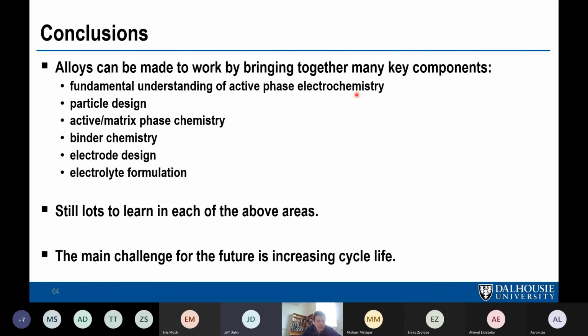So let's see what I said 3 years ago. You can get these things to work half decently, but you have to bring together the fundamental understanding of silicon electrochemistry. That had to come first, and then particle design to make the particles work. What's the interaction between the active phase and the matrix phase, whether it's a silicon alloy or SiO, you have the stress voltage coupling and other effects that can change the voltage curve, binder chemistry, design of the electrode, the electrolyte formulation and additives we talked about. It's a whole package really, from the particles all the way up to the cell design, all have to be custom made around any electrode, and that's really true for alloys.